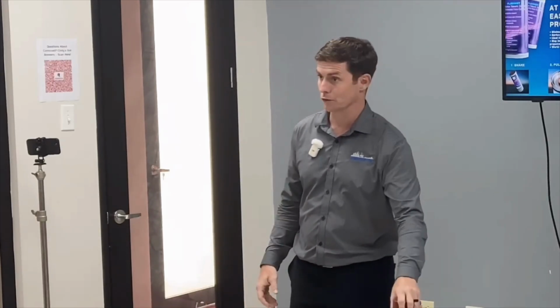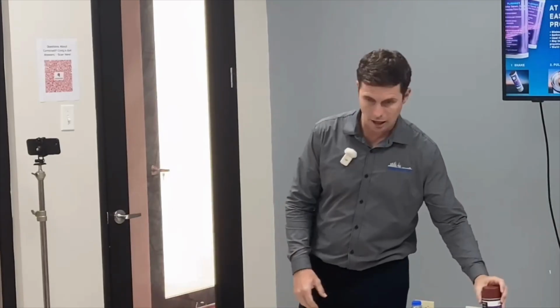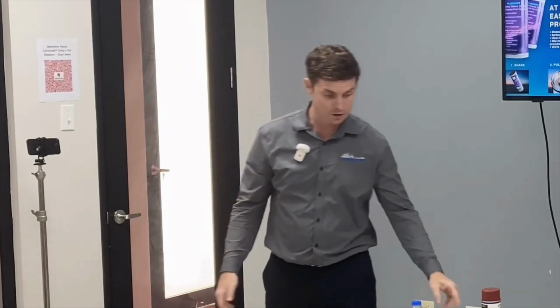Shell actually tested it to death, like Shell likes to do, to where if you use power tools to get an SP10, a near white blast using a bristle blaster, you can get 5 years. So if you do proper preparation, this can be more than just a temporary fix. And again, just like we were talking about the crevice corrosion, the corrosion problems that cause the most problems are the small areas. Now, you can see a big tank in a lot of corrosion. It's the things that you don't see or that you ignore that cause more headache.